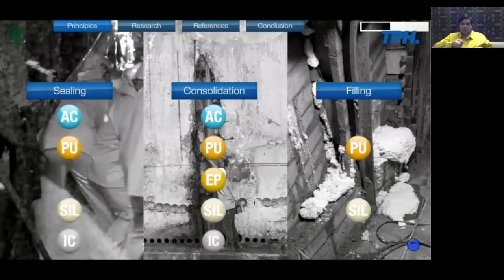Your PUs are good for sealing, consolidation as well as filling. Your epoxies are very good in consolidation, which is why they are used in repair for injection of cracks and repair strategies. Then your silicate based materials, again, they're very good. They can bind very, very well. They're low viscosity, so they can easily penetrate through, consolidate a lot of the strata, and the foaming ones can fill up a lot of areas. So the application is pretty much across the board. And your injection cements too can be used under these different circumstances.